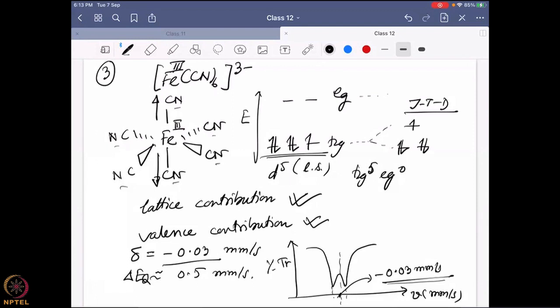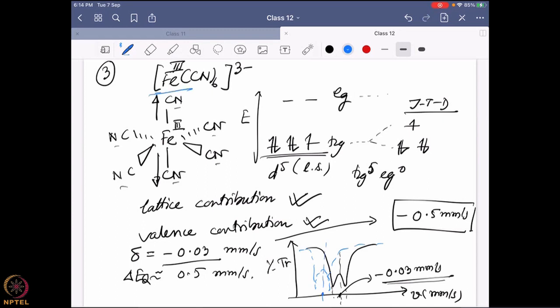But if you are able to measure at a similar temperature, then the value starts shifting. And at low temperature, it starts shifting close to minus 0.5 millimeter per second, a little bit farther on the negative side, which is expected for a higher oxidation state. So it is going to move to minus 0.5 millimeter per second. So you have to be very careful when you are discussing and comparing different oxidation states of a similar system like iron. You have to keep all the other experimental conditions as similar as possible. Otherwise, you cannot compare them directly.